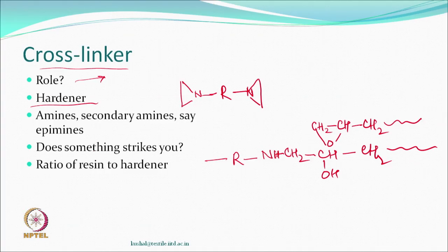In normal usage, you may probably require very, very little of these agents, but if you are looking at different applications, then you may use more. Then this resin to hardener ratio will decide the stiffness. As we said before, the aliphatic versus aromatic components, the ratio of these can also change the hardness. Similarly, here also one can use more or less or no hardener, which can also change the stiffness.